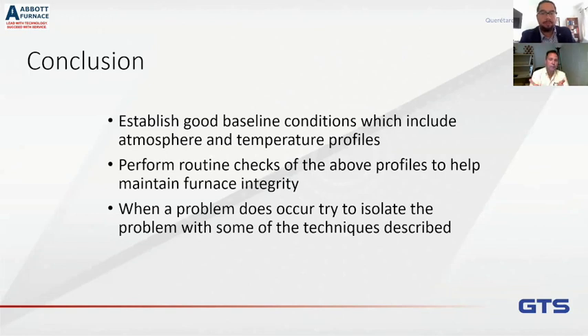Yeah, in fact, the most common element used to lower the melting point is boron. And if you have a high dew point in the front of the furnace, the boron can either oxidize, or if there's water vapor, it'll form boric acid and turn to a vapor. And you lose it. Yeah. It's funny because we have the same kind of issue with vacuum brazing, but it's a different mechanism. So boron is always a pain. Absolutely. It has a low vapor pressure. Yes, exactly. So boron is always going to be the problem in the filler metals. So Jose Luis, I hope this answers the question.